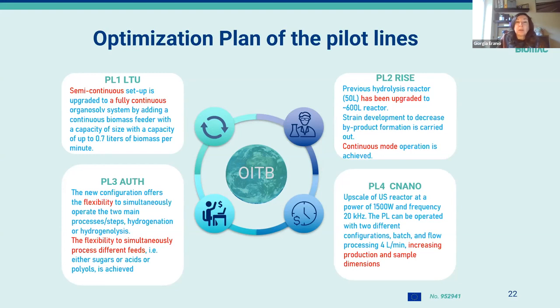So the first line, pilot line 1, managed to achieve a shift in the operation mode from a semi-continuous one to a fully continuous organosolv system, adding a continuous biomass feeder with a capacity of up to 0.7 liters of biomass per minute. Then pilot line 2, by RISE, managed to upgrade the production capacity, installing a 600-liter reactor. Furthermore, they managed to develop a strain to decrease the byproduct formation. And then they also achieved a continuous operation mode.